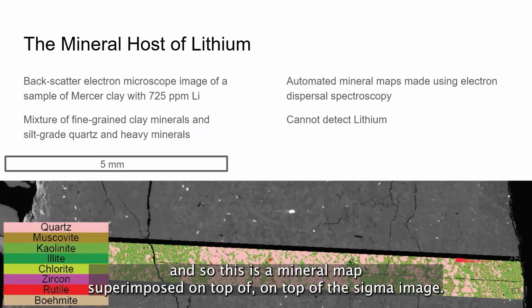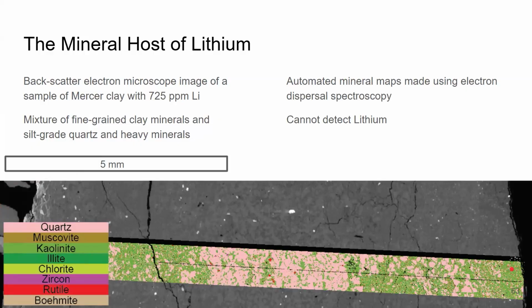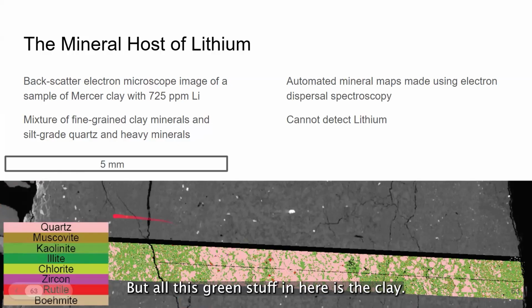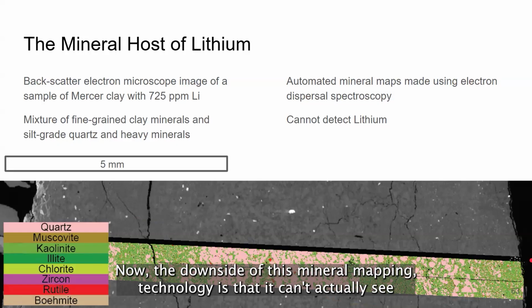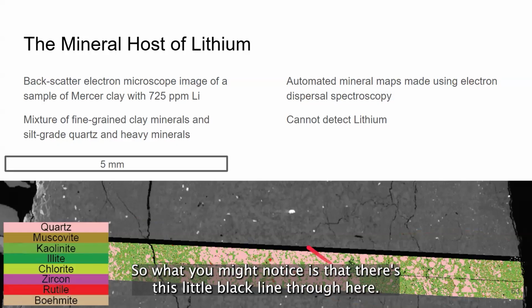And so this is a mineral map superimposed on top of the SEM image. The pink here is quartz. There's a little bit of red titanium oxide, but all this green stuff in here is the clay. Now, the downside of this mineral mapping technology is that it can't actually see lithium itself. So what you might notice is that there's this little black line through here.